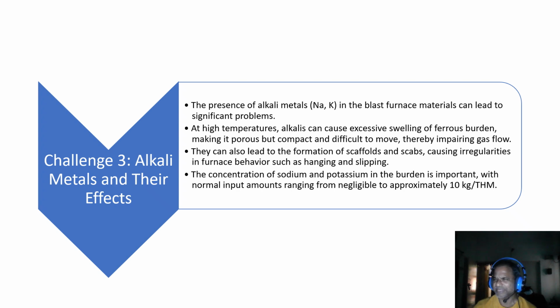severely impairing gas flow. Furthermore, alkalis are known to contribute to the formation of a scaffold and scabs on the furnace wall. This buildup causes irregularities in the furnace behavior, leading to undesirable events such as hanging and slipping of the burden. It's important to monitor the concentration of sodium and potassium in the burden, as normal input amounts can range from negligible to approximately 10 kg per ton of hot metal.